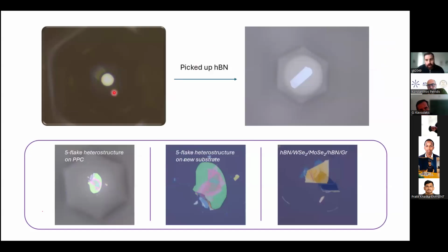So let's see here the control that we have over the process. We have a thin HBN flake here. I come in contact in the center, and I control the contact front basically. How is it controlled? Well, we developed code that calculates the centroid of the flake, calculates the distance from the centroid to the longest edge, and then the code says to the contact front, okay, now progress 10, 15 microns more than that. This way, we manage to have a uniform conformation of the polymer on the flake without taking anything on the polymer. We stop at the location that we want, and then we say to the system, okay, wait now until the temperature drops down to 40 degrees, and then start to retract to pick up the flake.